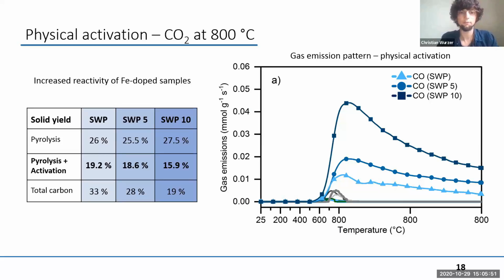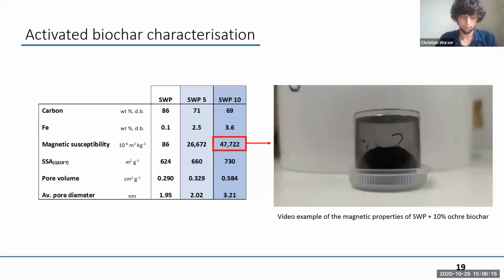To actually say if the whole process is beneficial or not, we have to take into account the total solid carbon yield that you see here, but also the increase in gas energy content, as you offset fossil energy usually used for heating your reactor. And more importantly, you also have to check the adsorption performance, as this will determine your product quality. So here, for the activated biochar characterizations of the solid product, you see some basic numbers, so carbon content, iron content, and also the magnetic susceptibility, which indicates how magnetic your biochar is.